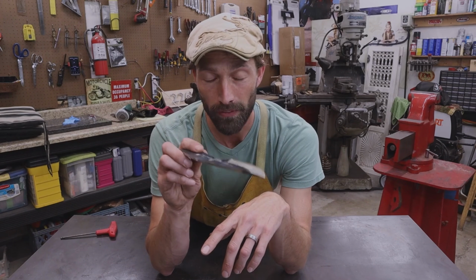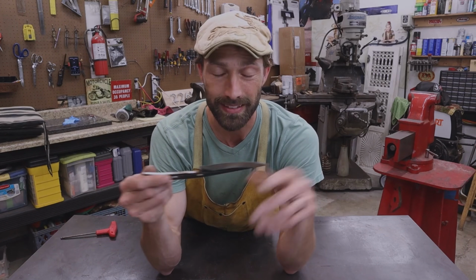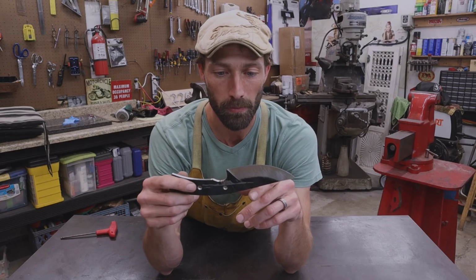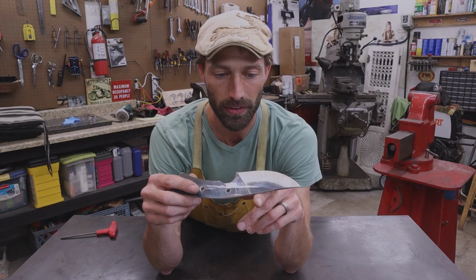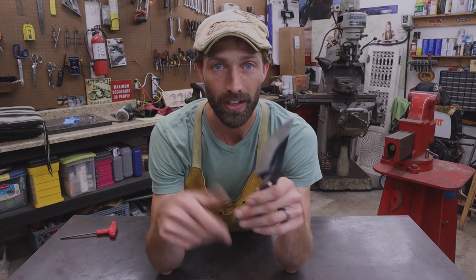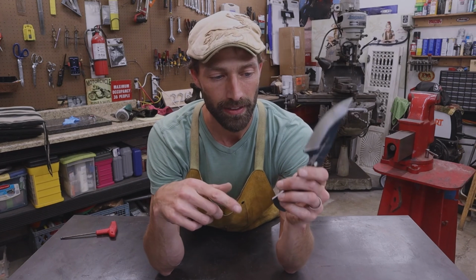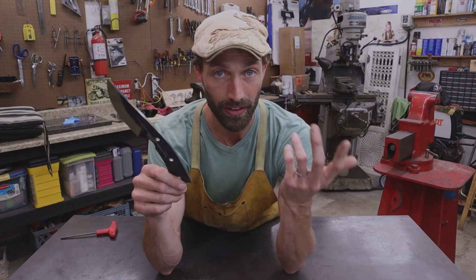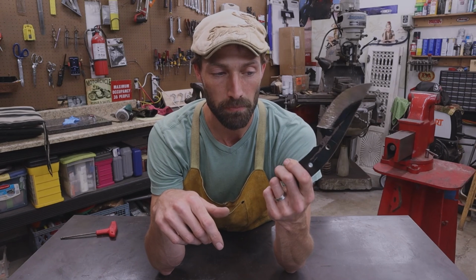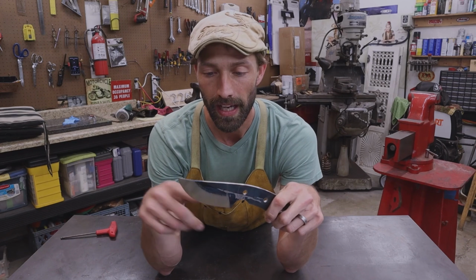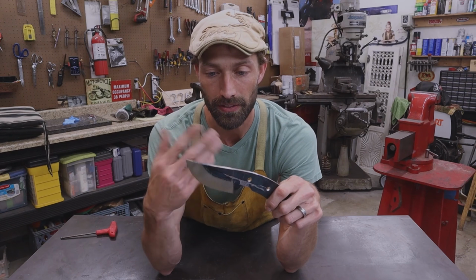I am gonna use my forge to heat treat this, but basically that's a torch that's inside of a housing. So it's the exact same thing. I just don't have a torch, so I'm not gonna go buy a torch just to show you how to heat treat with the torch. You guys can figure that out. Just fire up your torch, and what I would do is you're gonna need a good hot glove, but you could even put this in a vise while you're heating it, and you're gonna heat the edge until it's non-magnetic.